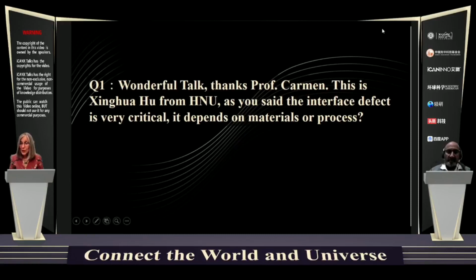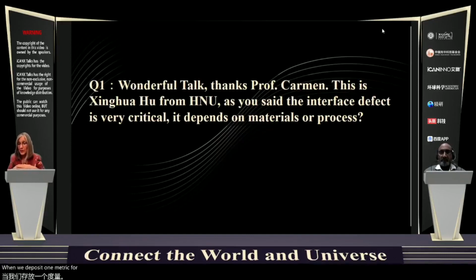It's actually both. I did not show results, but it is actually interesting that when we deposit one material, for example, hafnia on top of silica, it is not the same in terms of stress as when we deposit silica on top of hafnia. And this tells you that interfaces play a very important role.